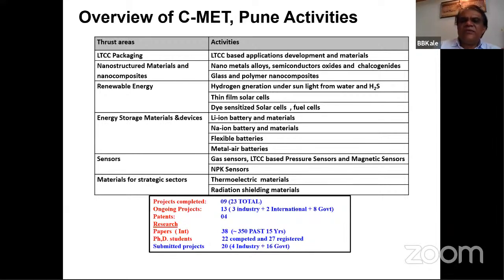So then all these nanostructures we use in solar cells, we use in fuel cells, we use in batteries, supercapacitors, because these nanostructures have wide applications. Maybe like in a battery, we synthesize cathode material and anode material because these are the main components in the battery. 80% of the material is only cathode and anode. So if you design a material from a very low scale, maybe 5 nanometer to 10 nanometer, we found that the capacity has been increased a lot.